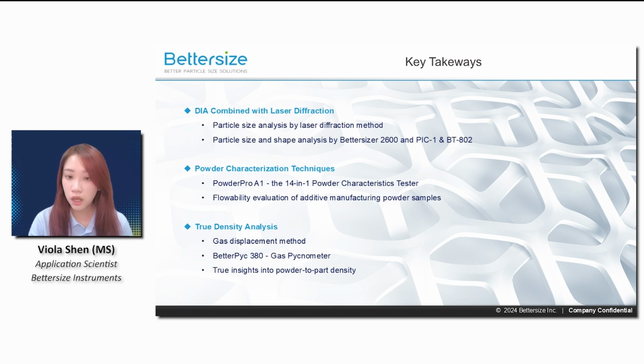The Powder Pro A1, a powder characteristic tester, serves as an integrated solution for assessing powder flowability, which is a key factor in achieving consistent layer deposition in 3D printing. Also, the BetterPyc 380 gas pycnometer utilizes the gas displacement method to ensure reliable true density measurements and supports the correlation between powder and final part density. With all these advanced tools, Bettersize empowers additive manufacturing industries to achieve greater accuracy and efficiency in material analysis and quality control.